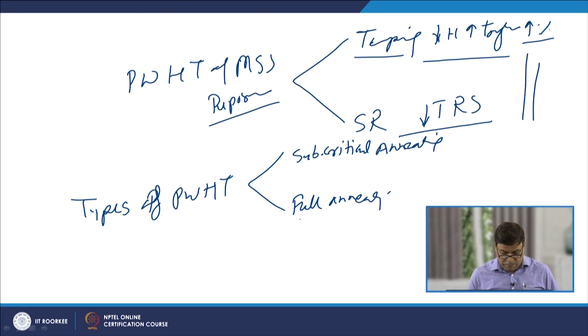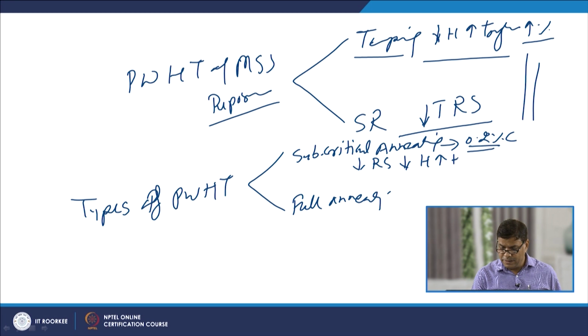Subcritical annealing is normally carried out in the temperature range of, say, 1400 to 1500 degrees Fahrenheit, and at a higher temperature the full annealing is carried out. The primary purpose of subcritical annealing, which is carried out for martensitic stainless steels having carbon content greater than 0.2%, is that it helps in reducing the residual stresses, lowering the hardness, and improving the toughness.